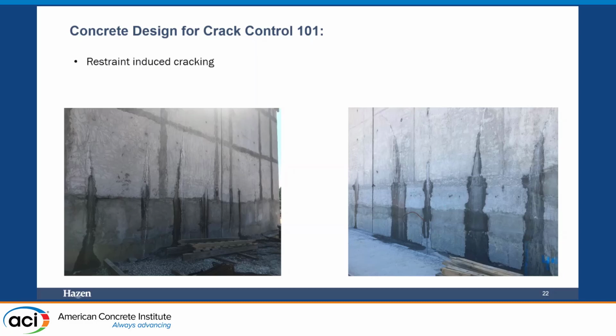This is an example here of restraint-induced cracking, where the cracking is present down at the base of the wall, but dissipates as you move up the wall, and that's a situation where the base slab for the tank has restrained the wall as the wall wanted to move after it's placed. And restraint-induced cracking is something that needs to be considered in the design.